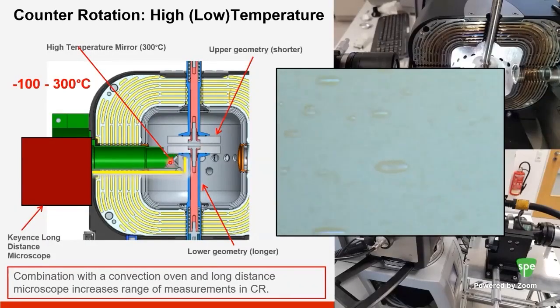So now you can do experiments at much elevated temperatures. Hopefully this is a video taken in a setup like this, the same PIB in PDMS type solution. So now you can see, using counter rotation really opens up where this droplet is stuck in the stagnation plane. Now you can image the dynamics and relaxation of this droplet for much longer, which is generally not possible when you just do rheo-microscopy on a single drive device.